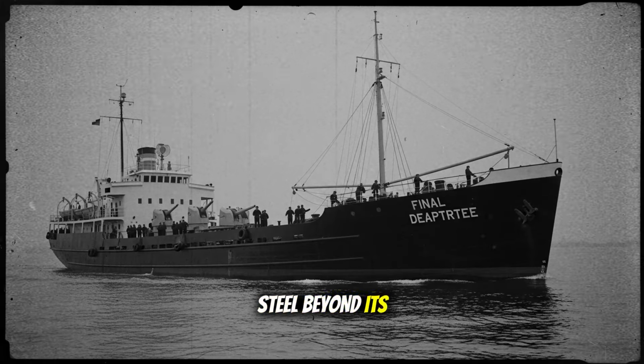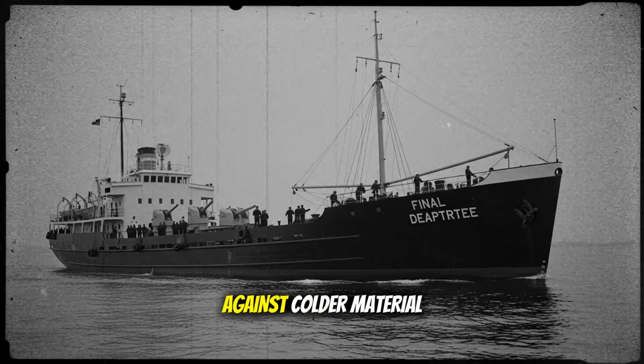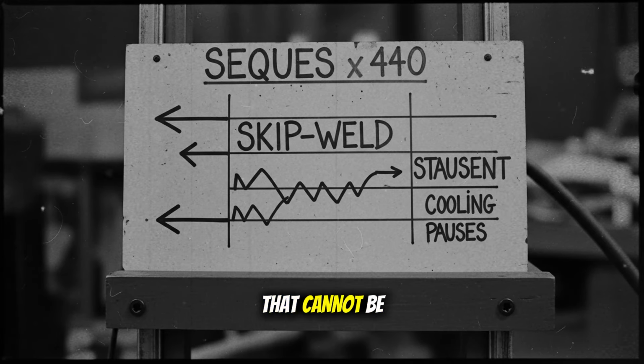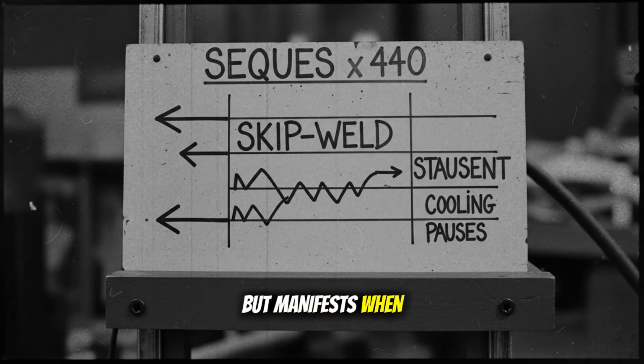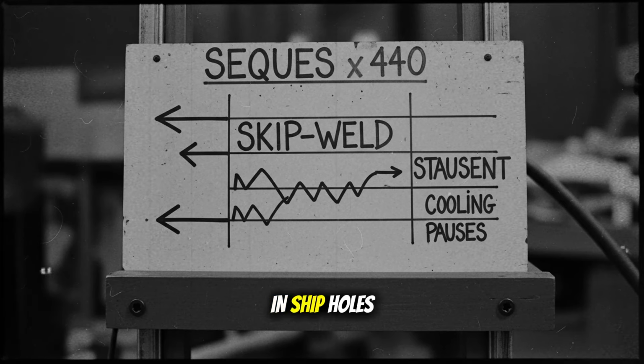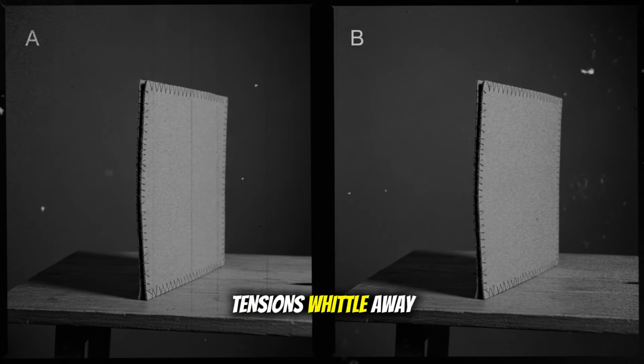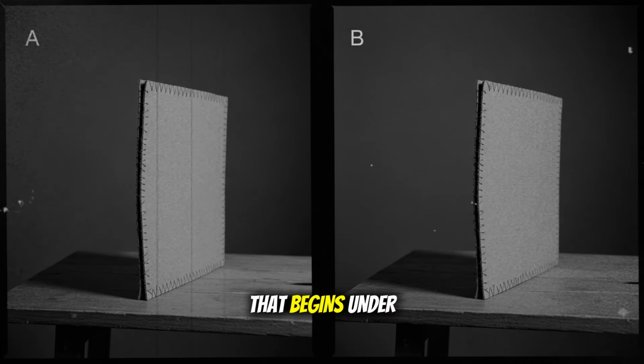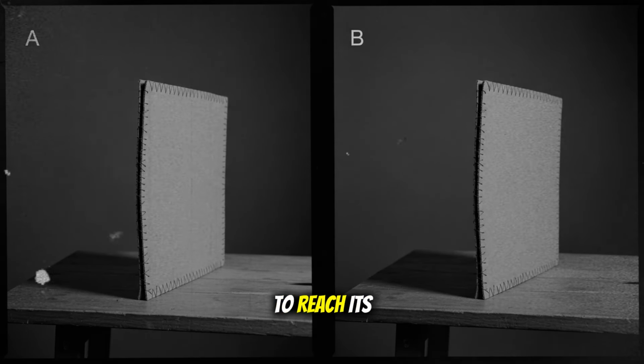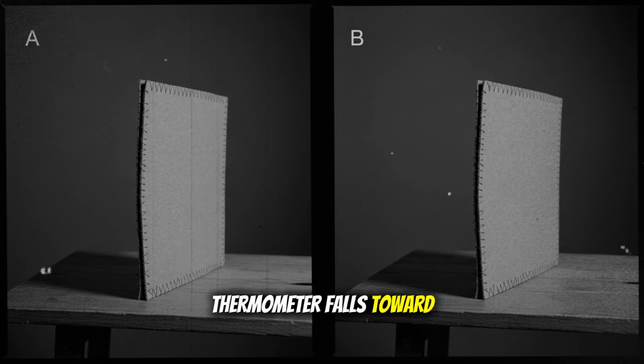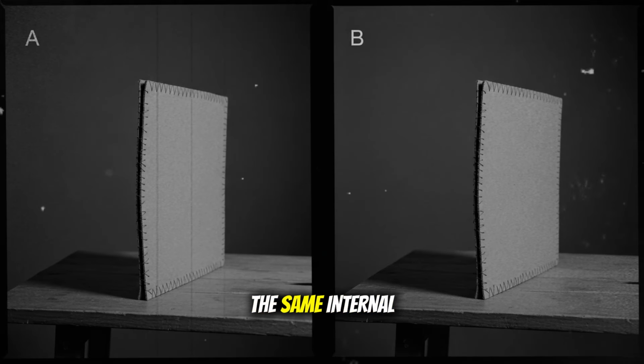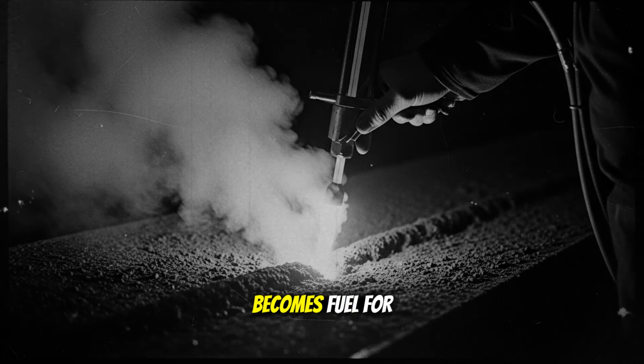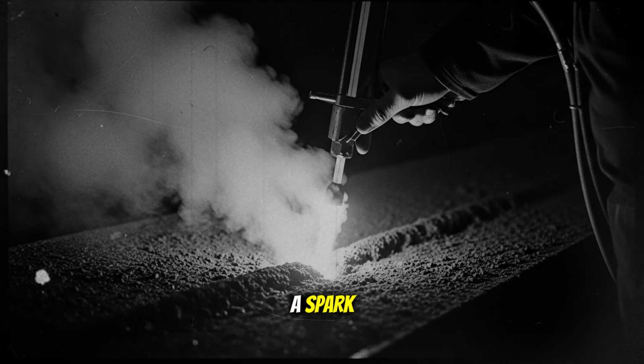Residual stress is the mark left by heat that expands the steel beyond its neighbors and then forces it to shrink back against colder material that refuses to follow, locking tension into the microstructure that cannot be measured by a tape but manifests when service loads and temperature conspire to add one ounce too many. In ship hulls, those locked-in tensions whittle away safety margins because a plate that begins under longitudinal pull needs less ocean to reach its limit, and when the thermometer falls toward the ductile to brittle transition, the same internal tension that meant nothing in the shed becomes fuel for a crack once a notch provides a spark.